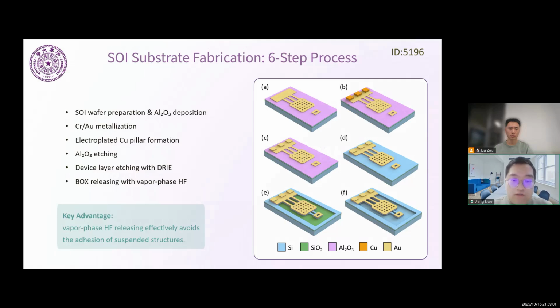Then we etch the device layer using DRIE to define the cantilever. And finally, we release the structure using vapor phase hydrofluoric acid. This removes the sacrificial oxide underneath. This gives us a freestanding, stress-controlled cantilever that is ready for bonding.